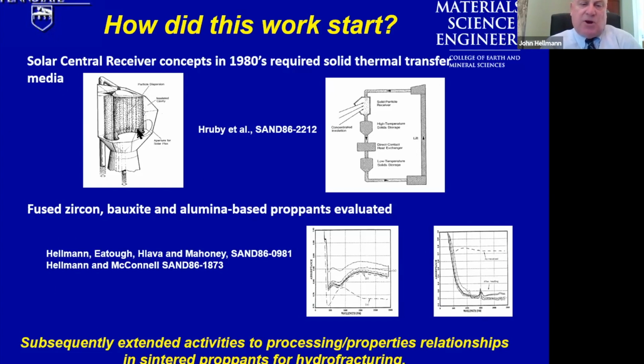This roughly 10-meter tall aperture through which the particles were irradiated yielded a residence time sufficiently long such that the particles would increase in temperature from about room temperature to on the order of 1500 degrees C, a very, very high intensity solar beam. These hot particles then would subsequently be stored and energy extracted from them to do industrial processing, such as cracking ethylenes, and then recycled through the system repeatedly over the lifetime of the system to capture the solar radiation, transform it into thermal radiation for industrial processing.